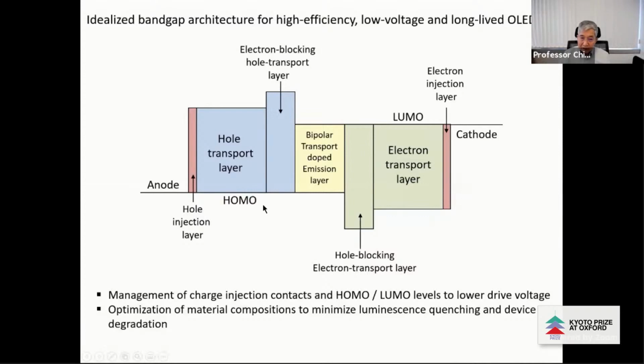Here, the key is this 3-layer here. One is to block the holes coming from this side, and the other one is to block the electron going from this side. And leaving in the middle a so-called bipolar transport layer with the doped molecules, the dopants that produce the desired light of particular wavelength.